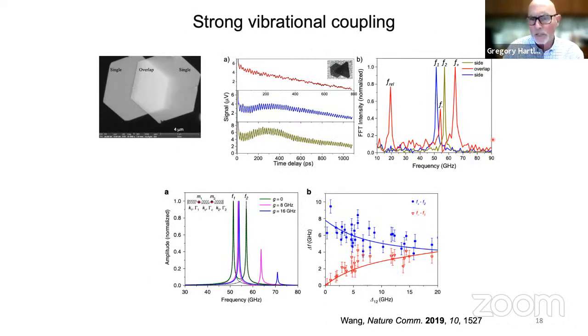One of them is to look at coupling. These are some experiments, again done by Kwai, of plates. When you drop cast nanoplates onto a sample, sometimes some of them overlap. So this is an image of 2 overlapped plates. In that case, you can do an experiment where you excite this plate here, or this plate here, or you can excite in the overlap region. When you excite either of the single plates, you see a single frequency. That's the breathing mode, and that depends on the thickness of the plate.